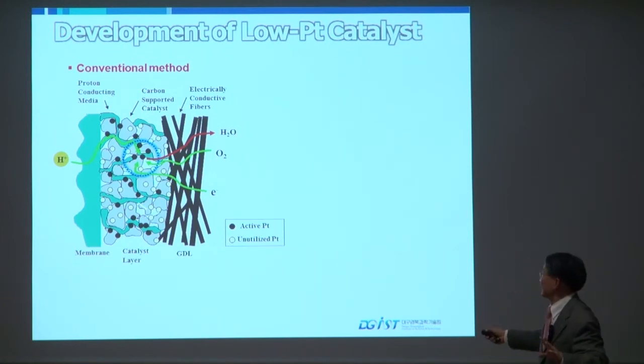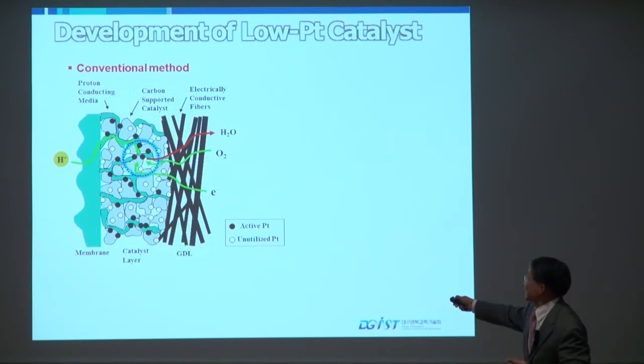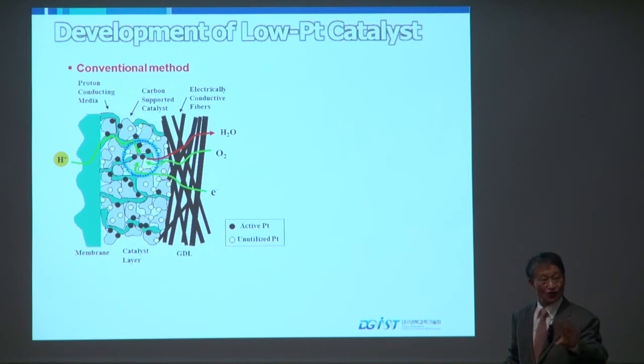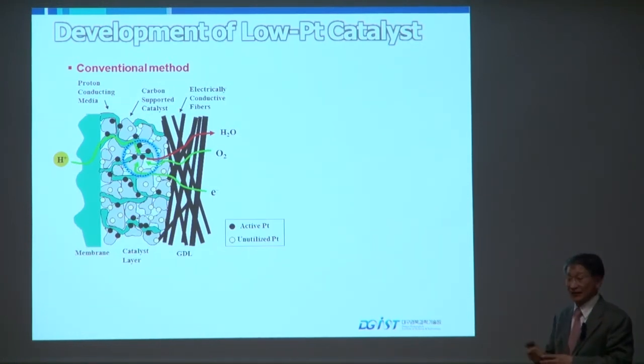Then it ends up like this. But many of these platinums are buried underneath or do not act as a triple phase site. That means they are dead catalysts. They are not utilized for fuel cell reactions. Only some part, perhaps in this black part, are active pieces, and the others are non-active parts.